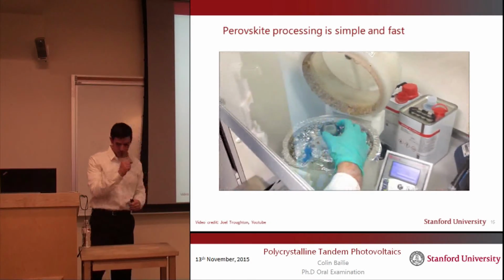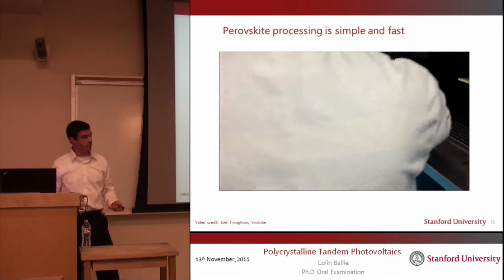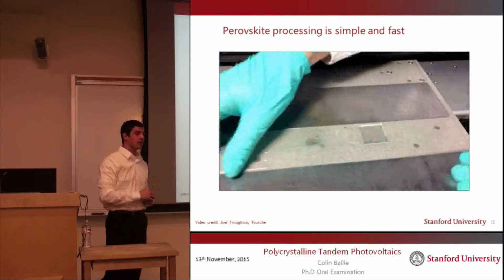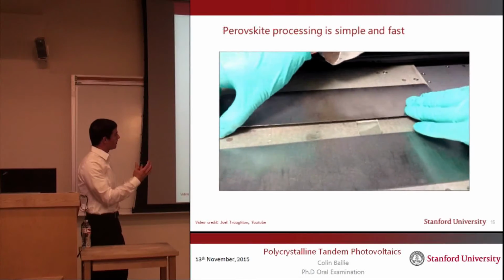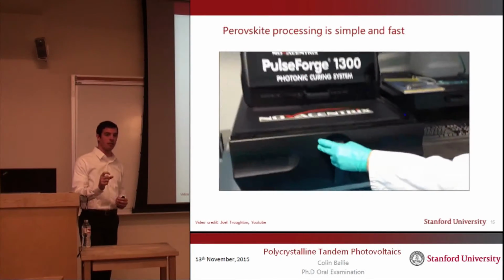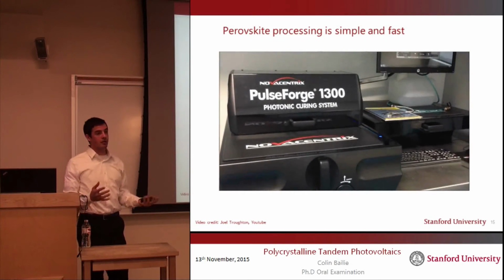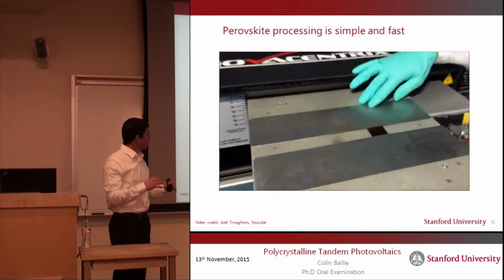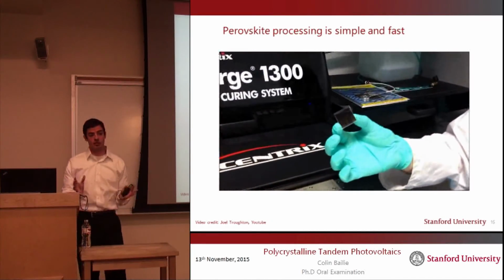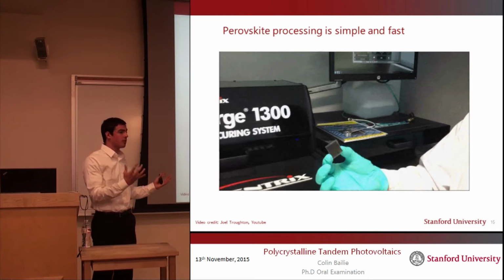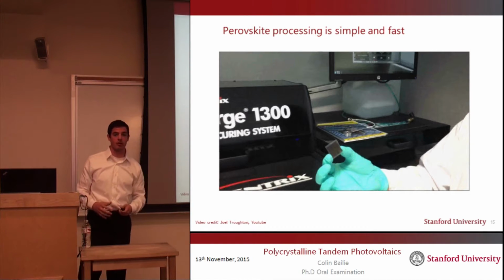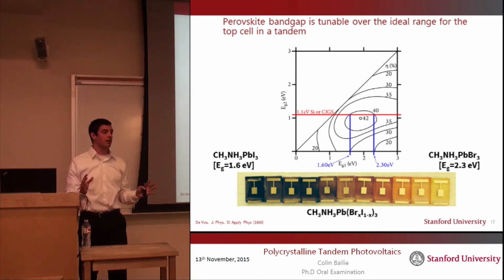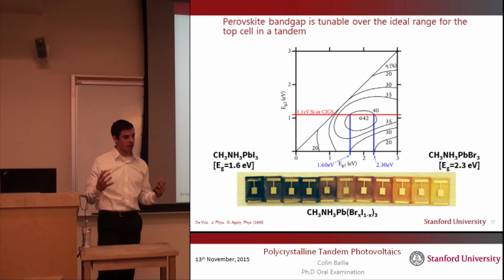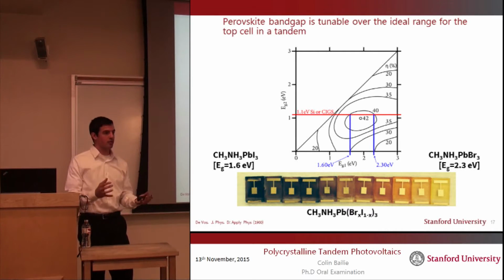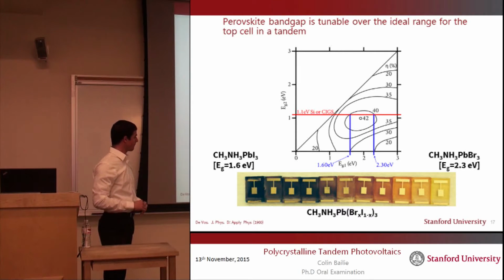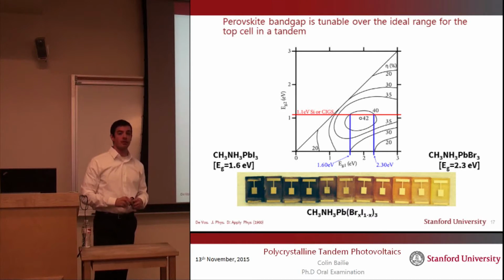This is a video that I got off of YouTube where a researcher printed down a layer of perovskite onto a glass slide, and right now it's clear because there's still solvent in the system. It hasn't formed the perovskite structure, but after only a millisecond of curing under this curing system, he got rid of all the solvent, and what you're left with is perovskite. And these are all necessary things in order to make a solar cell that is compatible with the low-cost requirements of today's industry.